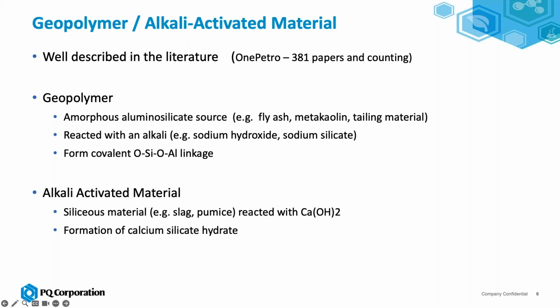Put into a highly alkaline environment, typically sodium hydroxide or sodium silicate, the oxides become hydroxides, and they can cross-link to form aluminate silica linkages. The other thing that sometimes gets blended in with geopolymers are alkali activated materials or pozzolans. So these are where the silicas become activated and can react with calcium and form calcium silicate hydrates. And this would be materials like slag or pumice.